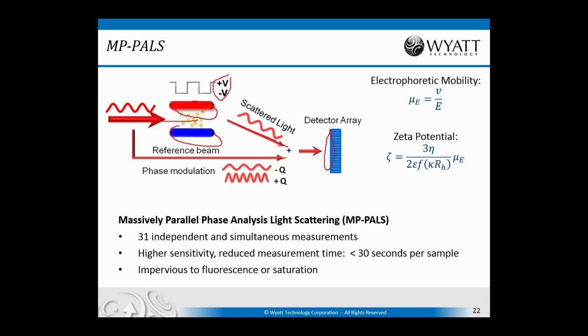And the velocity of the particles under the applied field impacts the frequency of the scattered light. By interfering them, we see slow oscillations on the detector array that are measurable using standard electronics. Those oscillations allow us to calculate the drift velocity under the electric field. The ratio gives us the electrophoretic mobility. And by combining the electrophoretic mobility with the hydrodynamic radius measured by DLS, we can calculate zeta potential.